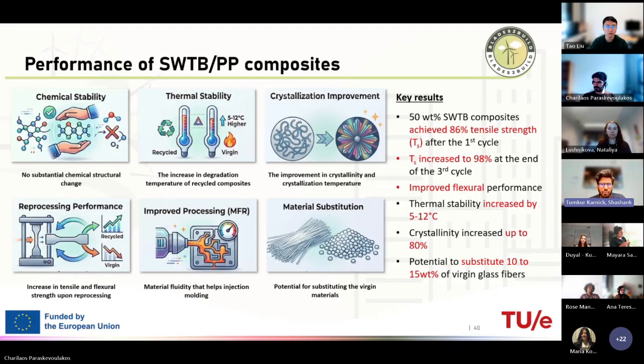the composition with 50% of wind turbine blade waste achieved almost around 86% tensile strength compared to the virgin glass fiber polypropylene composite. When we actually reprocessed it, the tensile strength actually increased to around 98% at the end of the third cycle, which proves that this composite material performs really well in comparison to virgin composites, which also has good flexural performance.